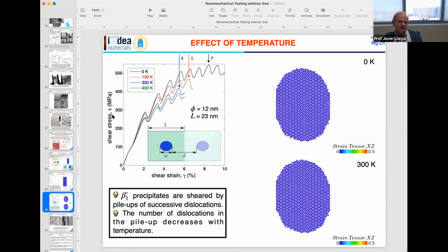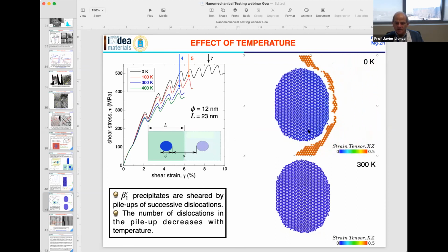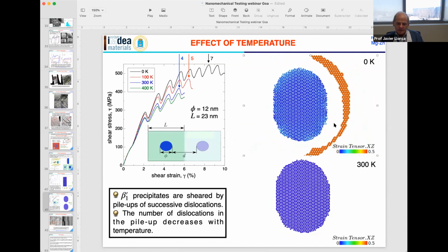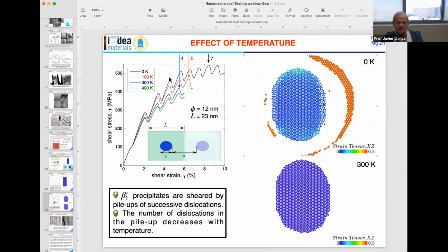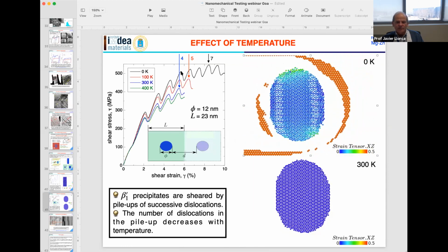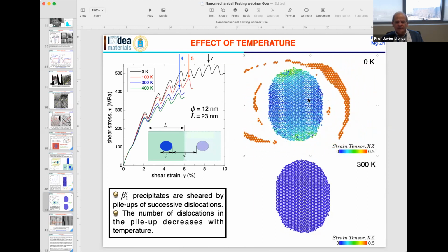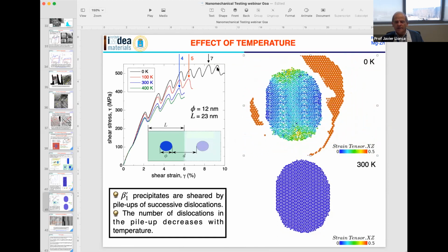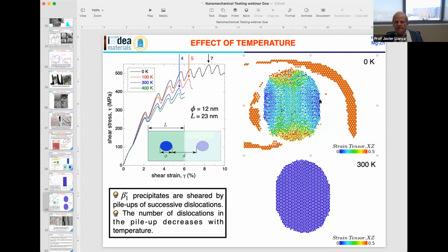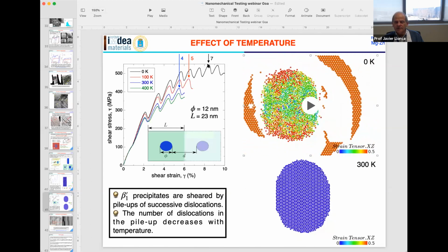So what you see here is basically the shear stress versus the shear strain. These are at different temperatures. The curve in black is for 0 Kelvin, 100 Kelvin, 300, 400 Kelvin. And as you can see, this point here indicates when the dislocation pile up is able to shear the precipitate. So this movie tells you what is happening at 0 Kelvin. First dislocation passes. Then the second dislocation passes, we are here. Then the third dislocation passes. And then when the fourth dislocation passes, the fifth, the sixth, the seventh, when we reach this point, you have been able to shear the precipitate, and the precipitate is completely disordered. So you get this value of the shear stress.